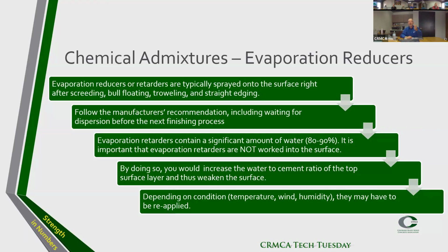Do not work the evaporation retardant into the surface, because you work the water into the surface, you increase the water cement ratio of your surface, and you weaken the surface. Depending on the conditions, you may have to reapply evaporation reducer. So that's just something to consider. Really helpful, but what I heard from several ready mix producers, they are quite often not correctly applied. So it really helps if the ready mix producer knows also how to apply them and make sure it's done correctly at the construction site.